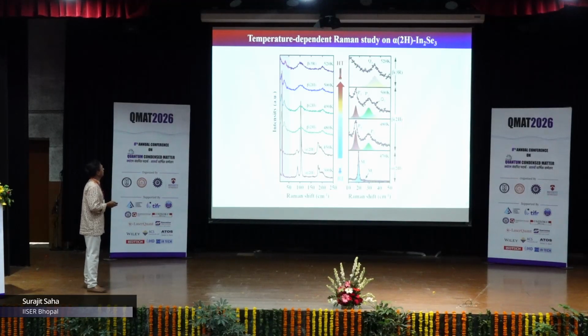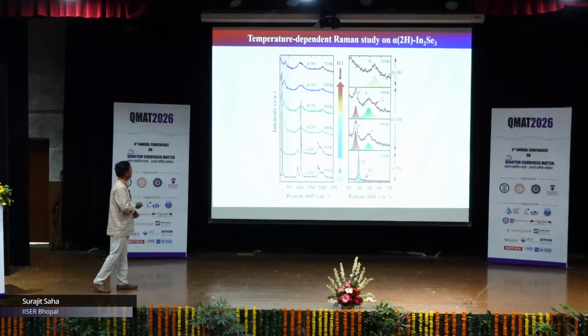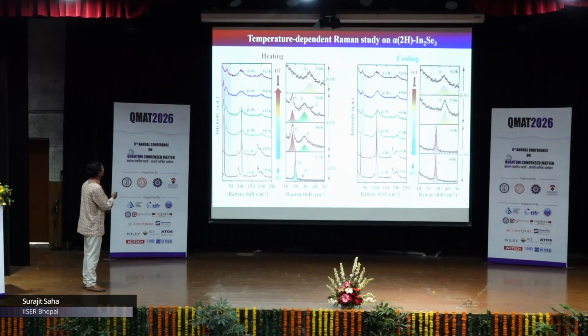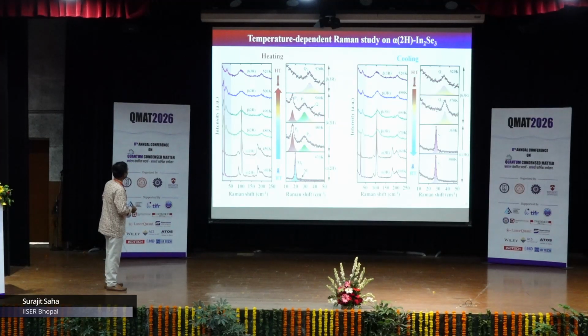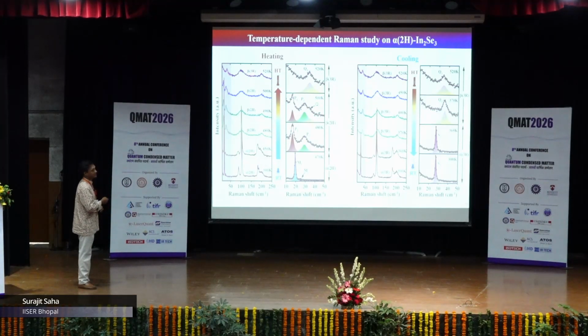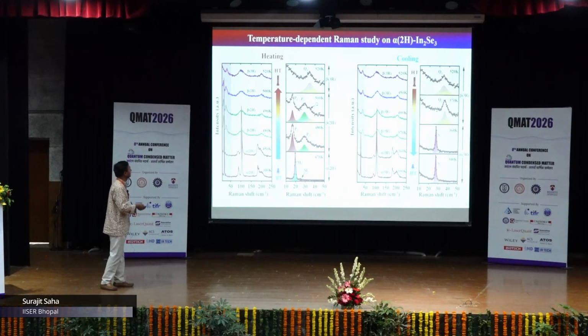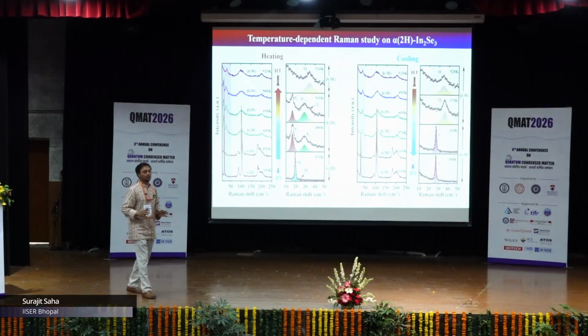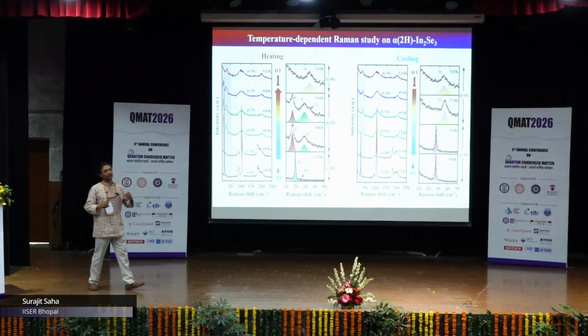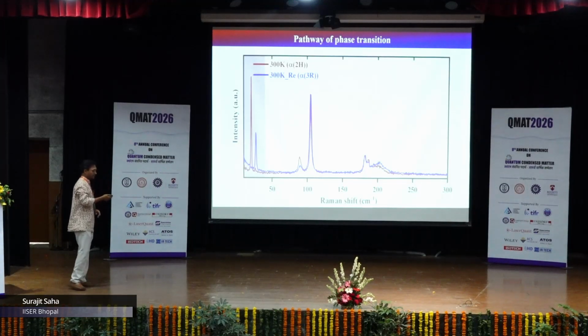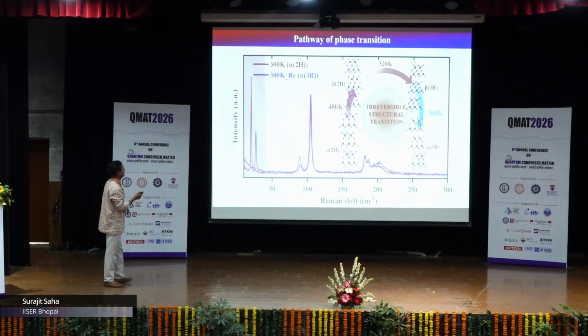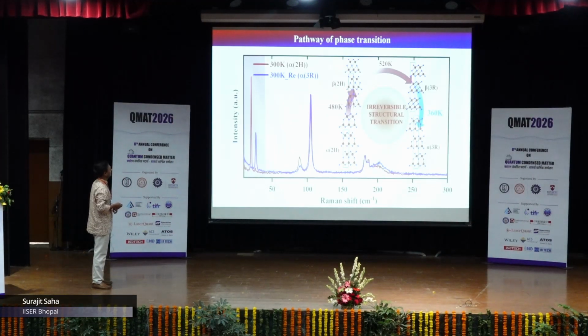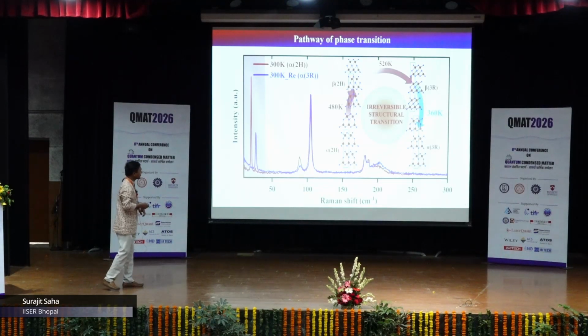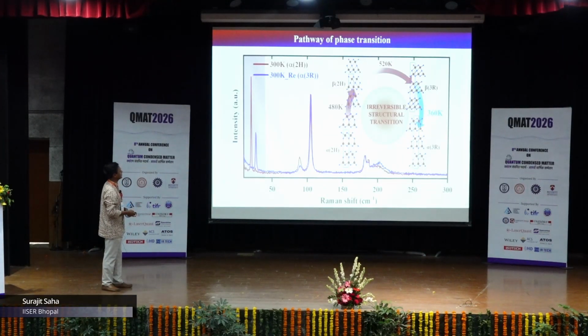Now, in the same way, if we look at the same alpha 2H and extend it to a much higher temperature, here you have gone to about 520 Kelvin, actually beyond. What we see now is that it not only goes to beta 2H, but it further goes to the 3R stacking. So at much higher temperature, it goes to the 3R stacking. And if you cool it back down, it does not come back to the 2H structure. So once it has transformed from the 2-layer structure to the 3R structure, it retains it. That's the irreversible transition as compared to the previous reversible transition. So we can summarize this in this way. Depending on the temperature that we go to, it can have a reversible transition from alpha 2H to beta 2H. But if you go to a much higher temperature, then we hit upon the irreversible transition to the alpha 3R phase.